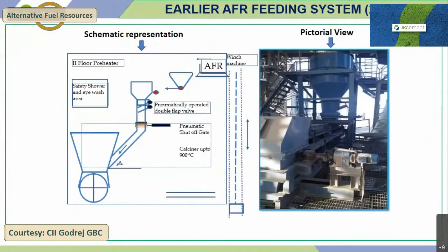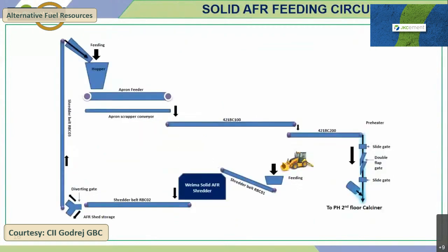This is the earlier feeding system when we started our journey for AFR. It is a normal buffer hopper with a belt conveyor, feeding directly to the calciner, in which we were able to feed around 1.5 to 1.7% TSR. Then we upgraded our system with an imported Vecoplan AFR shredder with a capacity of 20 TPH. After that, this material goes to the buffer bin with an apron feeder of 20 TPH capacity.